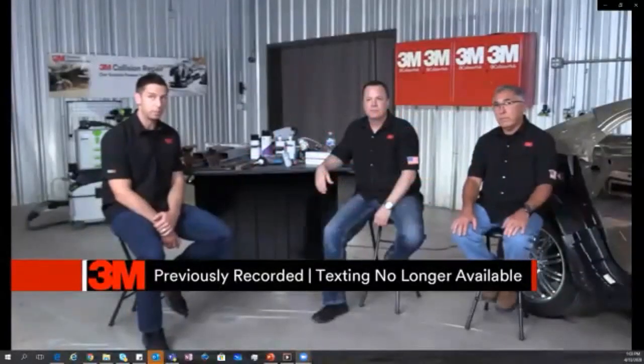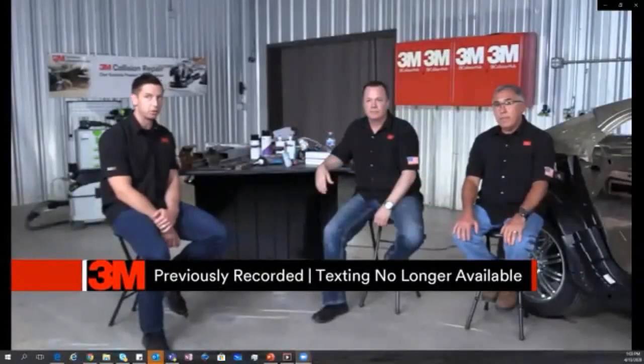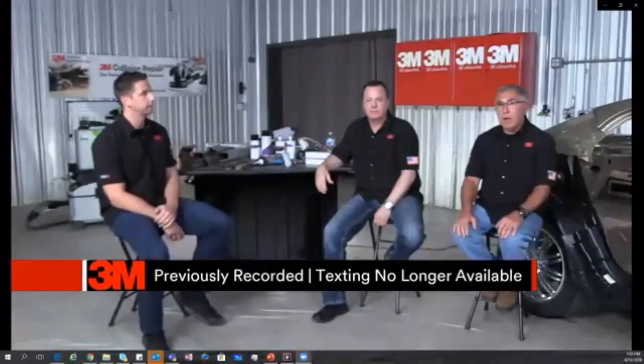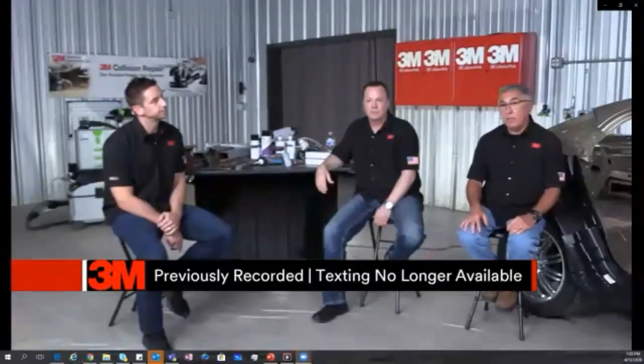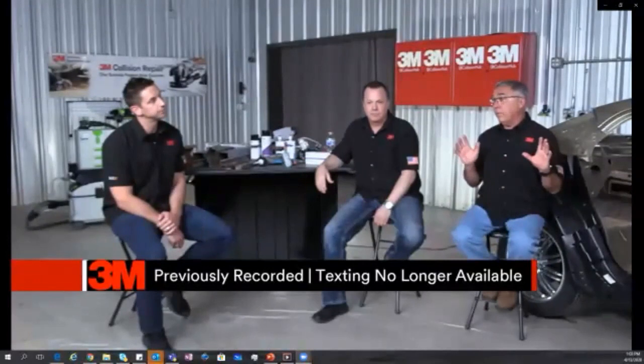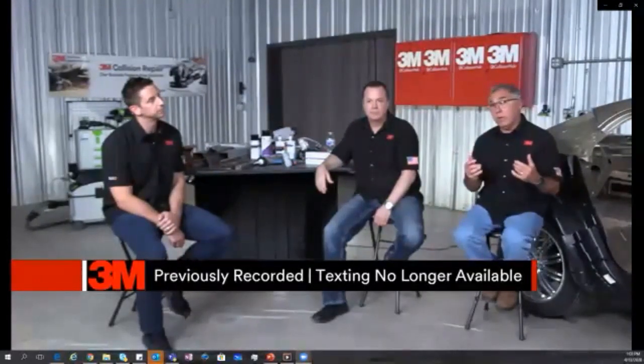Isn't it better to use epoxy primer inside of a closed cavity and sectioning location before cavity wax? Yeah, well, that kind of gets at what we were just talking about. So if there was burn charred paint in there and I sprayed it with epoxy primer, and that was the school of thought a few years back, but since then it's kind of changed, because if I sprayed it with epoxy primer it would dry to a dry film, and if it was on burn charred paint and soot, it would just flake off. Okay. So if I put cavity wax over it, it would just flake off.